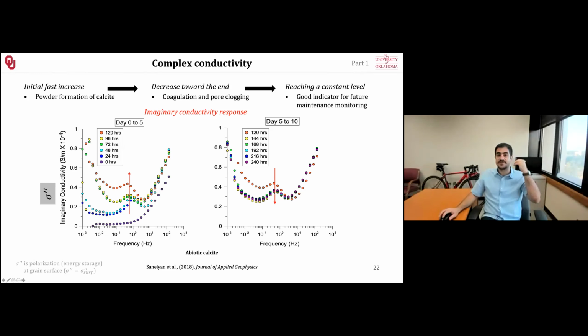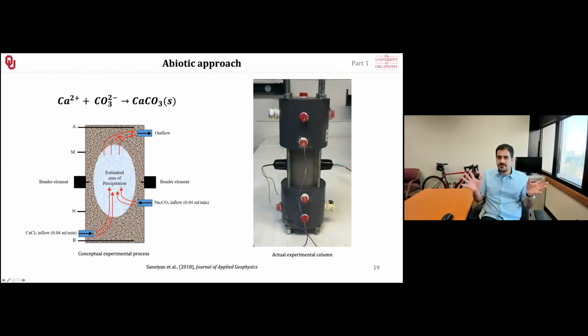So basically the surface area is reducing from that peak after a few days and reaches a kind of constant level, showing us that the calcite is no longer increasing in surface area inside the pore spaces. It's probably the equilibrium, where the same amount is getting precipitated as the same amount that's getting flushed out or dissolved in the water. Or the area in the middle that we were measuring in here is now fully saturated with precipitated calcite, and we are not sensitive to any area around here outside of these potential electrodes. So if the calcite is precipitating in here, we don't know it, honestly.